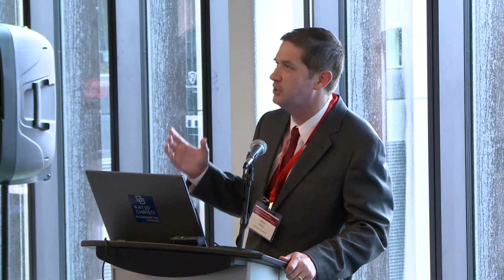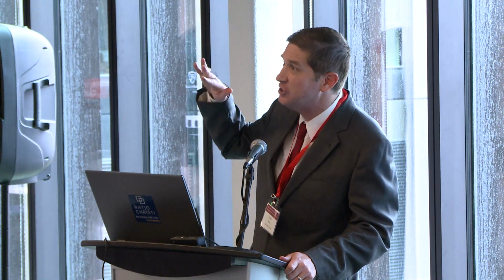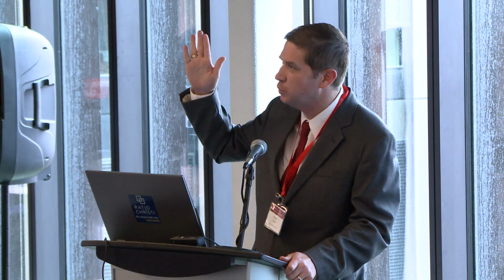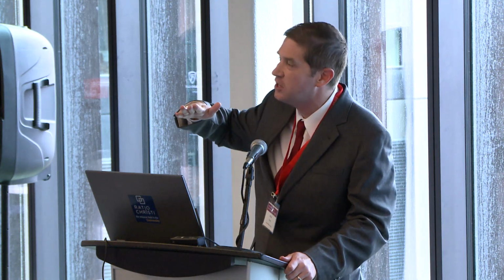Just to continue on to some of the work that's going on in my own group, one of the things we've become known for at Texas A&M is using electric fields on nanomaterials. It turns out nanotubes heat up like crazy in response to electric fields, and that turns out to be really useful for lots of practical applications. But one of my students also noted recently, there is some stuff in the literature on how nanotubes will actually align in response to these electric fields. And so he did a series of experiments where he showed, yes, the nanotubes will align in response to the electric fields, but they also heat up.